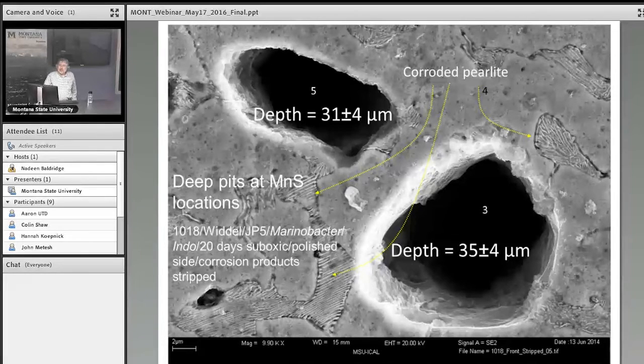You take a spectrum from the surface, you take a spectrum from the bottom of the pit, you know the absorption coefficient of the X-rays at that energy, and you compare it; you can get the depth. So that's something we published. Anyway, to the people out there, if you want it, we can lend you our software. You can have this as part of your SEM analysis. You will get this kind of information within seconds once you get the data. All you need is two spectra, one from the bottom, one from the top. You feed the data into the software, and within a few seconds you will get that information.